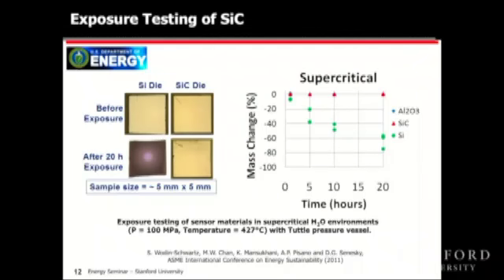When we're talking about placing these components in geothermal wellbores, it's important to demonstrate that this material actually withstands supercritical environments. So in wellbores, there's supercritical water that actually cuts steel. So can this silicon carbide material survive in that type of environment? This is an image of a silicon die, again, the material you find in your laptops. After 20 hours of exposure to supercritical water, it erodes. The silicon carbide die before and after, you can see no measurable change in the mass of the silicon carbide.